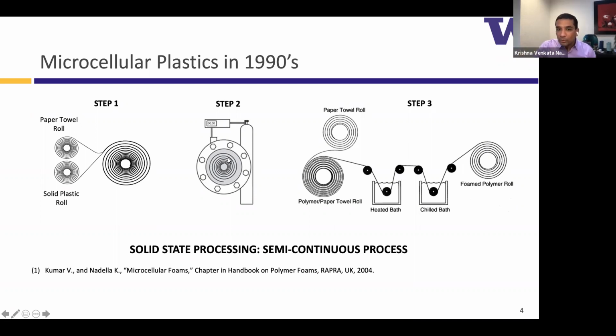You get some CO2 gas somewhere between 1 to 7% by weight in, and then you remove the roll and unwind it through a heated liquid bath followed by a chilled bath. And the paper towel is recollected so you can reuse it again and again.